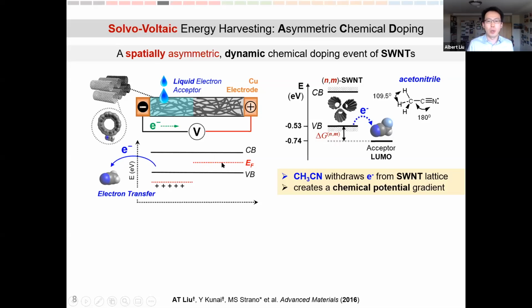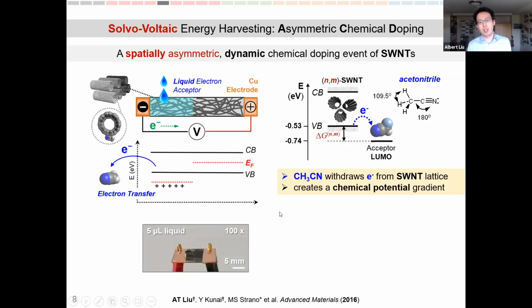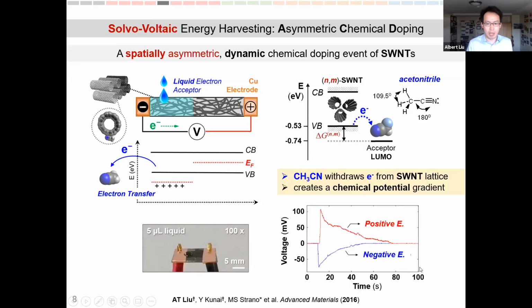In doing so, we can create, again, an imbalance of the chemical potential gradient across the network of the carbon nanotube, and that will induce a flow of electricity. So experimentally, this is very easily done. As you can see, you can just pipette a droplet of acetonitrile or other solvent doping molecule asymmetrically to the lattice of carbon. And as a result, you would produce a positive or negative voltage depending on where of the electrode you drop a chemical dopant.